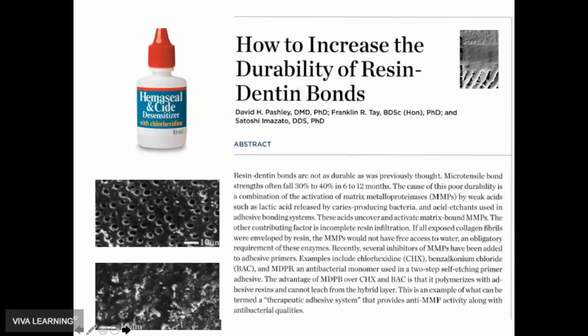How to increase the durability of dentin bonds? This is something to remember from Pashley and Tay a few years ago, and the release of MMPs, or matrix metalloproteases, that happen when we etch dentin. This particular product, Hemaseal & Cide Desensitizer, has chlorhexidine in its makeup. And when applying a desensitizer, the role of desensitizer is to plug the tubules, yes, but the chlorhexidine is going to help inhibit the release of MMPs from collagen, thereby increasing the durability of the dentin resin bonds over time.